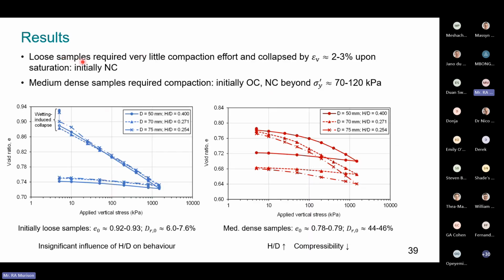The loose samples were considered to be initially normally consolidated for two reasons. Very little compactive effort was required to form the samples, so there was no significant stress history applied to them. And each of them also collapsed by 2 to 3% upon saturation, meaning that they were initially in a metastable state that was only attainable due to suctions in the sample. So we see that collapse over here.